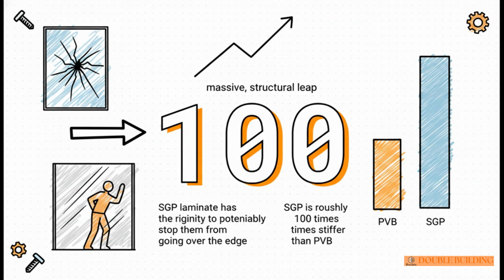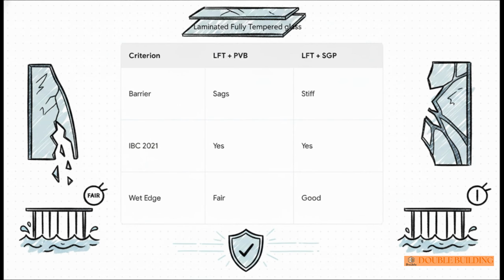If someone falls against a broken panel, an SGP laminate actually has the rigidity to potentially stop them from going over the edge. When you put laminated, fully tempered glass with both inner layers head-to-head, you see some really distinct differences. While both beautifully meet the base IBC 2021 code requirements, SGP dramatically outperforms PVB in structural retention. When broken, PVB offers a limited barrier because it just sags, while SGP offers significant stiffness. And for wet environments, like pools or coasts, SGP offers good edge stability compared to PVB's fair rating.